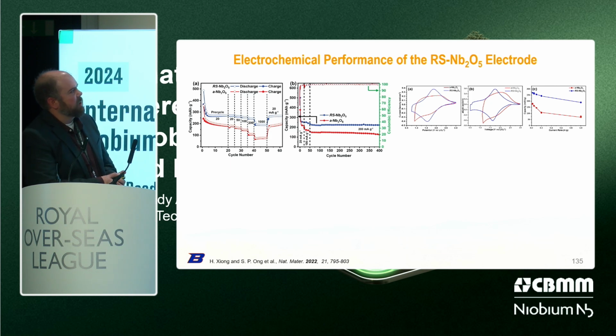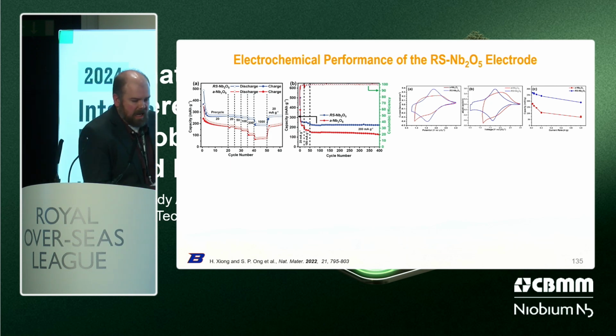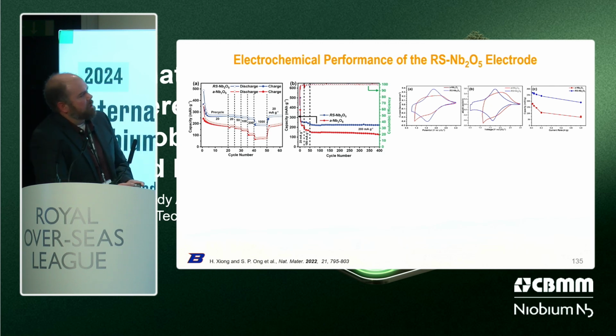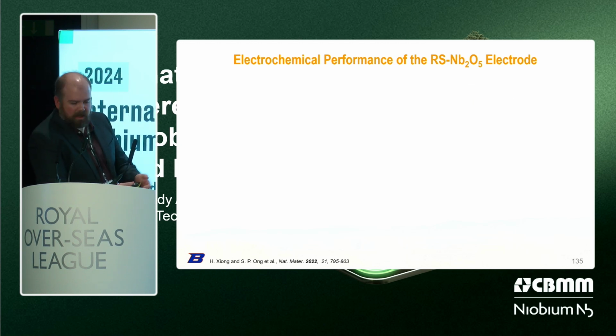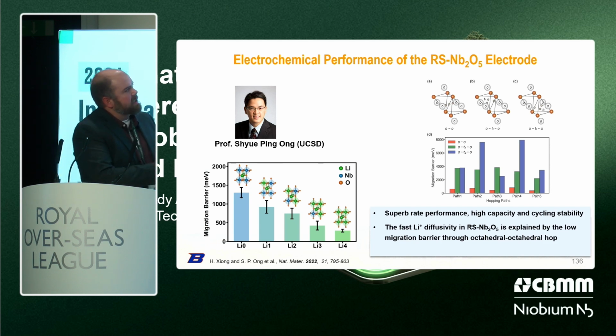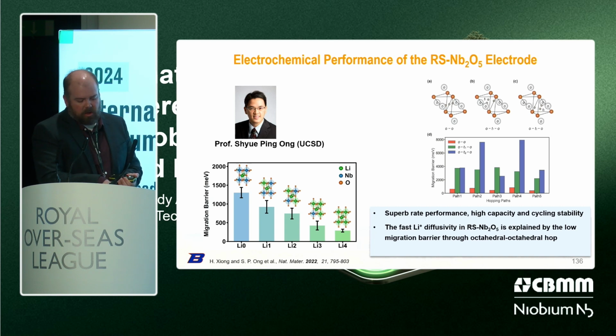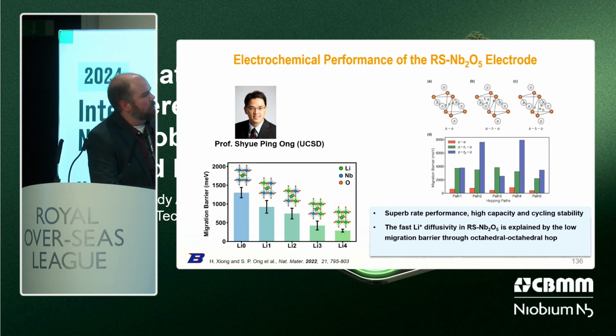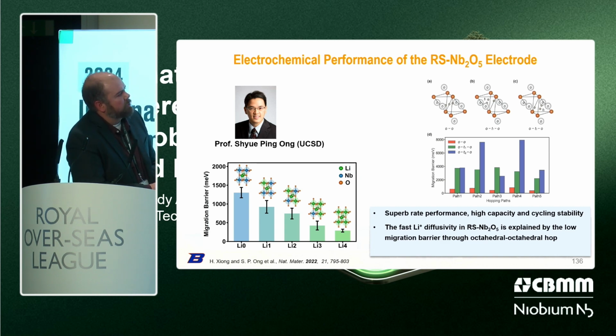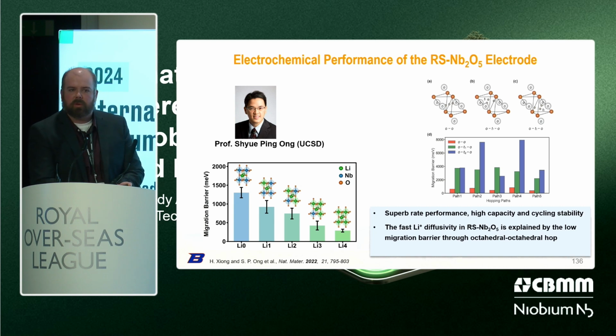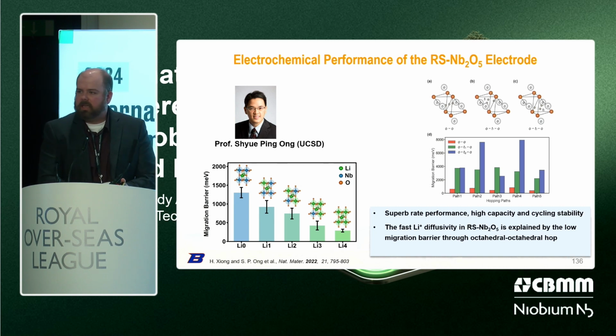And you can kind of tell this also by looking at the current densities as they go over the voltage, how different they are in comparison to amorphous to rock salt, right? This has that kind of characteristic capacity type response where the rock salt has that of the normal battery that we would like to witness. And I think I'm kind of getting out of time, but why we're seeing this fast lithium diffusivity was studied by Professor Shyue Ping Ong, where you have this octahedral to octahedral jumping for the lithium. So it's creating these little highways for the lithium to transport through the materials, where it's getting blocked in an amorphous type material.